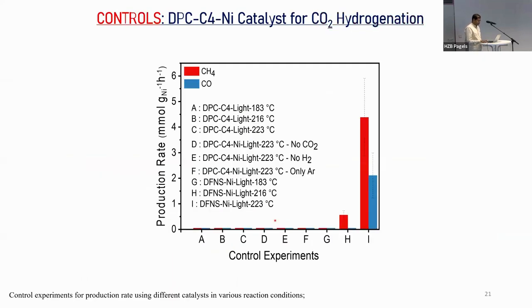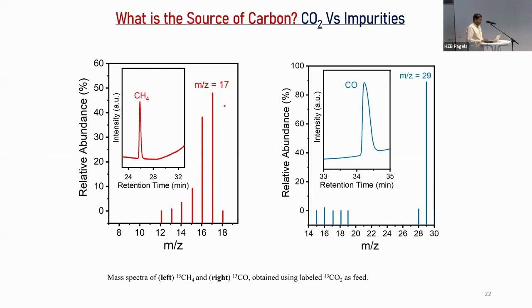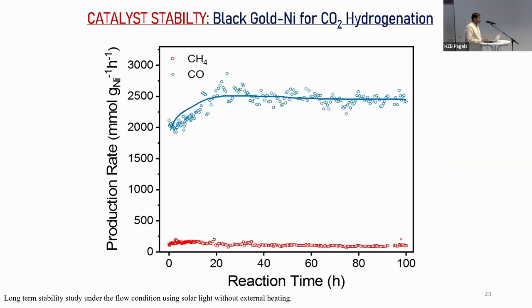We did some control experiments to make sure that it is only the black gold nickel. We also did labeled experiments to prove that the product you are getting is from the CO2 and not from some impurities. Anyway, this is the flow, and we carried this out for, I think, 100 hours, and you look at the stability, it's extremely stable. You see some increase in the initial hours.